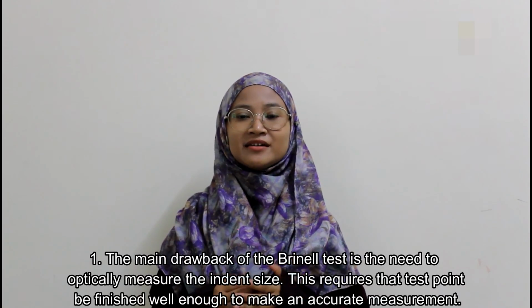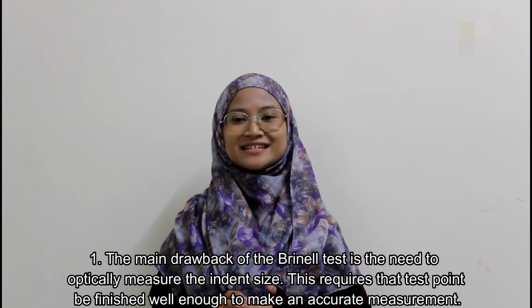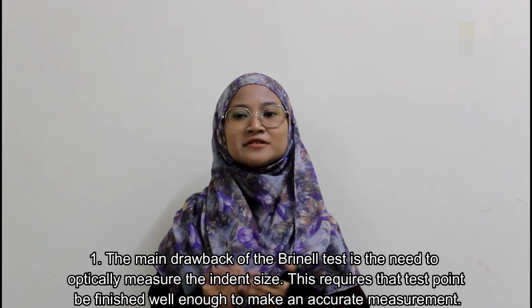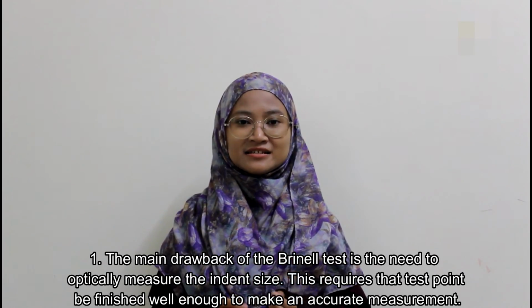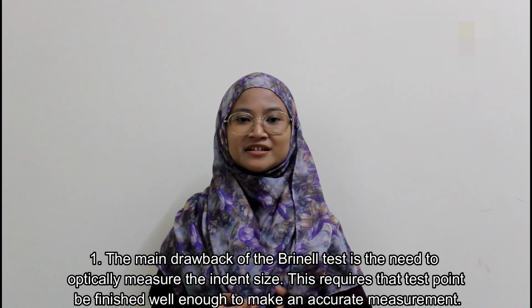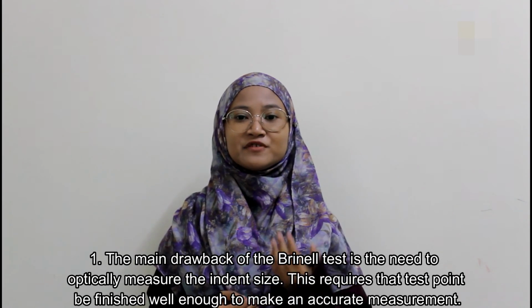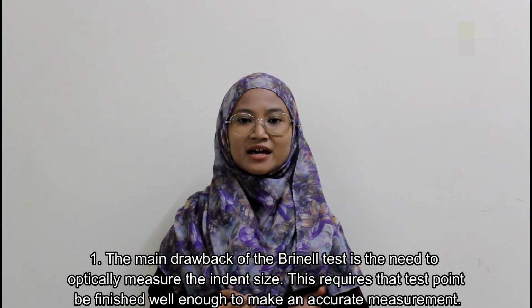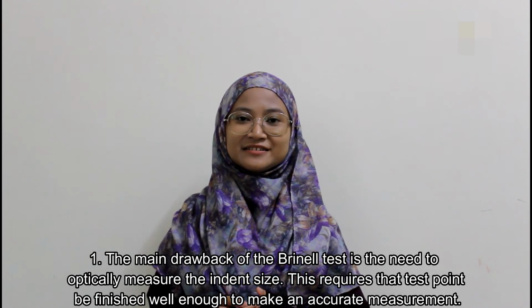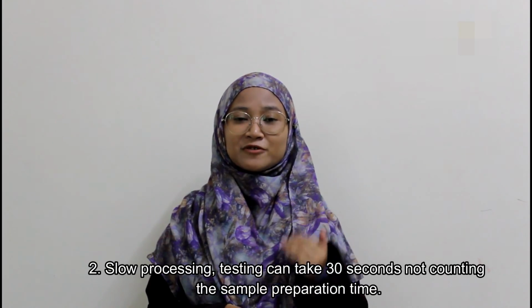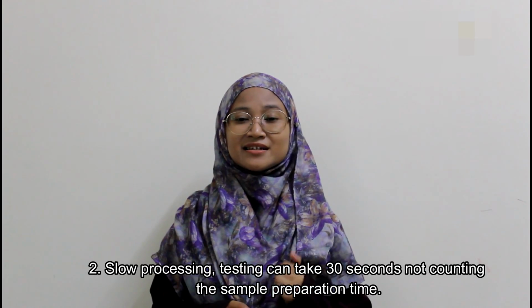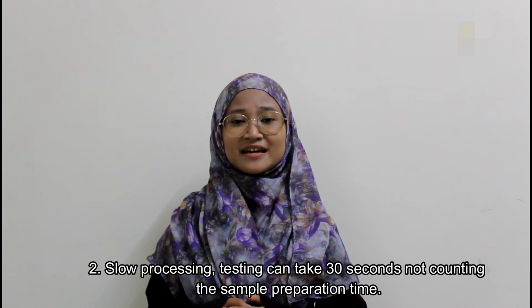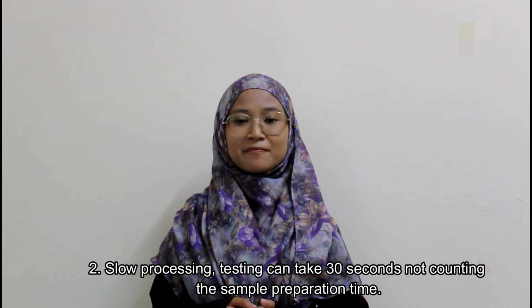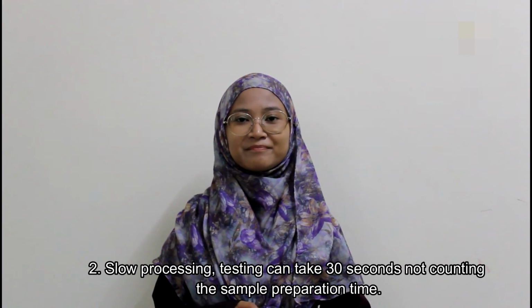Lastly, for the weaknesses, first, the main drawback of the Brinell test is the need to optically measure the indent size. This requires that the test point be finished well enough to make an accurate measurement. Then, this process is slow. Testing can take 30 seconds, not counting the sample preparation time. That's all from us. Thank you.